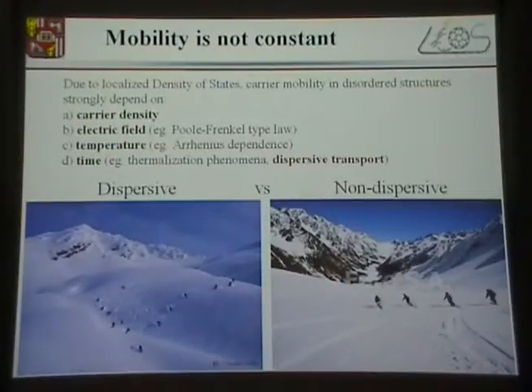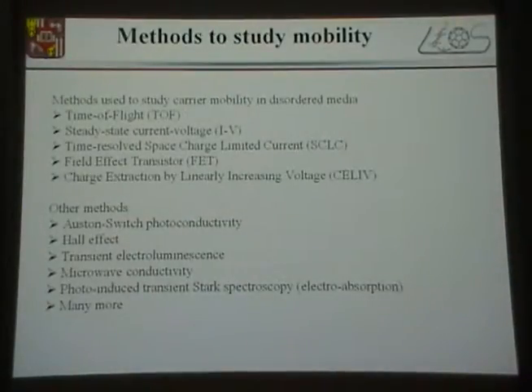This actually completely disturbs the measurement, first of all, and also the device performance, because the charge carrier mobility cannot be high due to the localized states and because of the hopping transport. So I will briefly show you the methods, which are not the only ones that I list here, but the most common ones used to study charge carrier mobility, charge carrier transport: the well-known time of flight, steady state, IV current voltage measurements, and all the rest of them. But mainly, I concentrate on the CELIV, and I will show you in a second why.